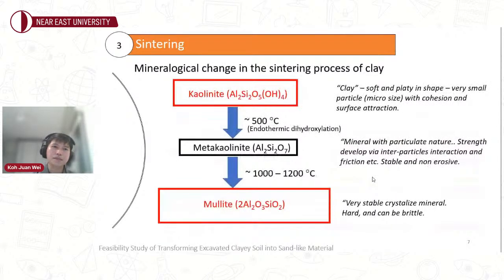And this slide shows the mineralogical change in the sintering process of clay. Normally clay has mainly kaolinite in the natural state. After we sinter it above 500 degrees Celsius, an endothermic dehydroxylation process occurs and it transforms into metakaolinite, a more stable and non-erosive mineral. When you heat further to 1000 or even 1200 degrees C, it transforms into mullite, which is very hard and sometimes brittle. But for our product, we mainly focus on transforming it into metakaolinite.